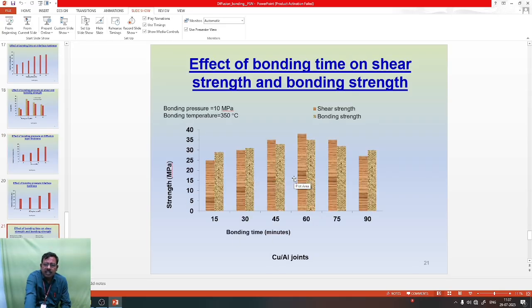Effect of bonding time on shear strength and bonding strength. Here bonding time is mentioned in the x-axis, the strengths are mentioned in the y-axis. So here at the bonding time 15 minutes, initially the bonding strength and shear strength are less. When the bonding time increases, these two strengths are increased. Up to 60 minutes, these two strengths are increased, after which the strengths are reduced. Because when the bonding time is higher, the diffusion layer thickness will be increased by the diffusion of atoms. Whenever the diffusion layer thickness increased, the shear strength and bonding strength are very less because of the intermetallic compounds.